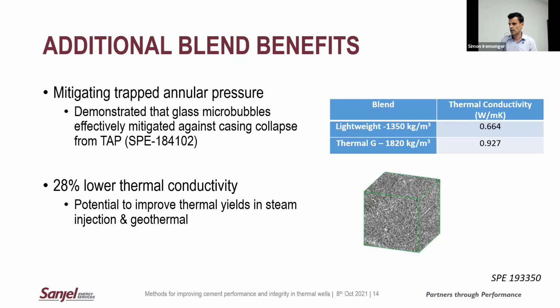Also, since you've got these hollow glass microbubbles, we do see a substantially lower thermal conductivity, 28% lower relative to that of a traditional thermal Class G cement. So, I thought that could be interesting. Maybe there's some potential to improve thermal yields in steam injection, or on the geothermal side, potentially an advantage here for these systems.